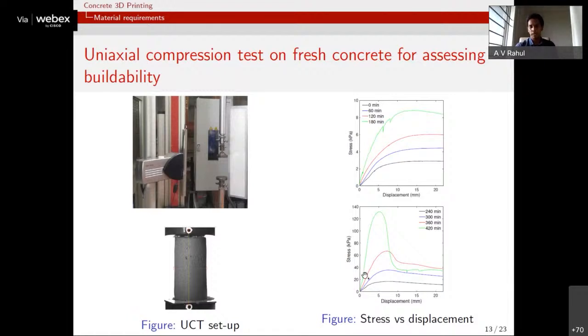Now, here you're looking at stress-displacement, but you can convert that to a stress-strain graph. If you take the slope of that graph, you can capture the elastic modulus, and the maximum stress that you see in this graph gives you the compressive strength. If you cast the specimen and do the test after different rest durations, you can see the evolution of compressive strength, and similarly, you can see the evolution of elastic modulus.